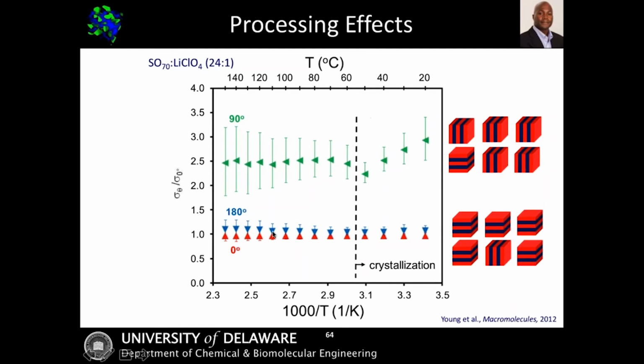One of the first things that we saw, again in a PS-PEO material doped with a lithium perchlorate salt, is shown here: the conductivity at a given angle normalized to the conductivity of the initial sample at 0 degrees. So obviously the 0 degree sample is at 1.0. On the right side, we did in situ small angle X-ray scattering and were able to calculate the relative fraction of lamellar grains oriented either perpendicular to the direction we were conducting, which is up and down, or parallel to the direction we were conducting the lithium ions. In this bottom case, slightly above 80% of our material was in a direction that didn't promote conductivity.